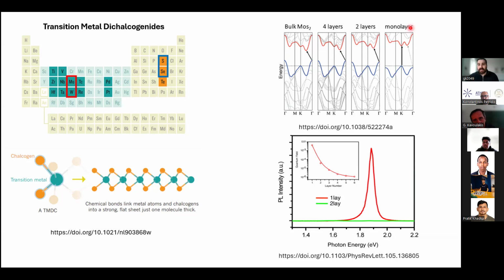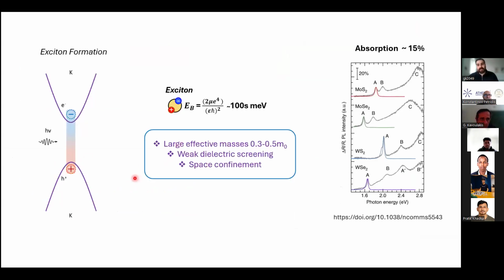And this actually gives rise to a PL emission from a single layer of these materials. And let's get into more on how this PL emission happens. You excite the material with energy equal to or more than the energy gap, and one electron is promoted from the valence band to the conduction band, leaving behind a hole. Now, this electron will interact with this hole via Coulomb interactions, and it will form a quasi-particle called an exciton. When this exciton, after some time, recombines with the hole, it emits light.